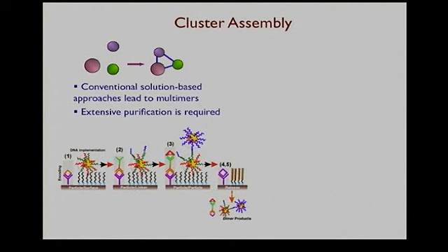So we have a surface which is functionalized with DNA grafted to the surface, and we have particles which have two types of DNA. One is intended for hybridization with the surface, and the other for something other, which you will see right away. So what the surface really does is allow us to block half of the particle. So when we add, let's say, another particle which has complementarity to another type of DNA, it will end up here, and this particle will be rejected by the surface. It's not going to adsorb because this interaction is not recognized.